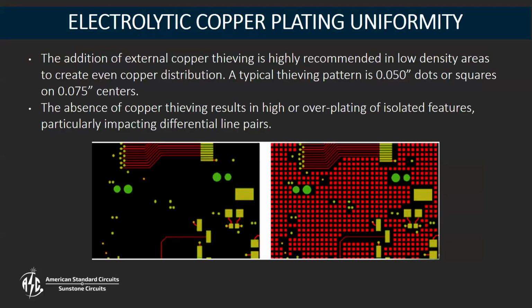Adding external thieving, especially on the external layers, also helps with plating, creates more even copper distribution. If you add, like, 50 mil dots or squares, they recommend on about 75 mil centers. It's not necessarily electrically active, but it does help with the distribution of electroplating. A lot of times, if that's added, that'll get added by our CAM tooling as well. But having that on internal layers also helps with that resin distribution a little more than just bare laminate would.